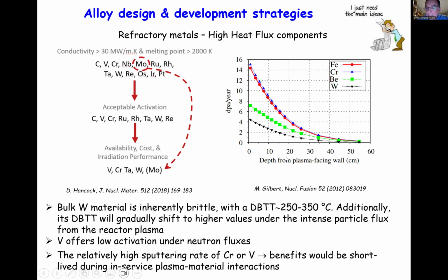Now, if we look at the susceptibility to radiation damage, so the amount of DPAs per year as a function of depth from the plasma-facing wall, imagine the plasma is at 0 on the x-axis, and you see how much damage that material will undergo as a function of depth and time. Then you can see that iron and chromium, which are components of steels, are relatively quite susceptible. Beryllium is less, but it's toxic.